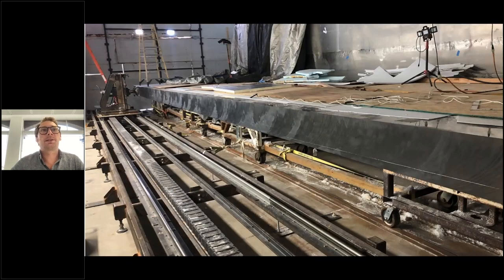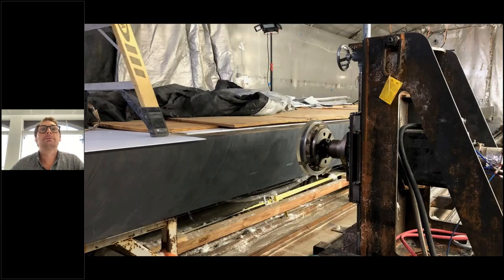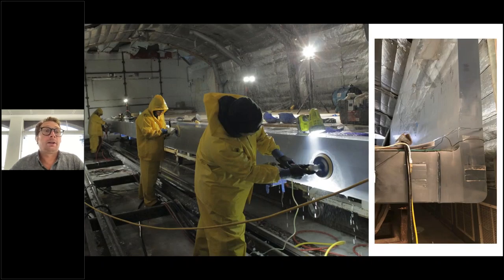And you can see here that the slab on the right-hand side is supported on tracks, so it could be wheeled out and turned around by a crane, so each side can be accessed. And you can see the milling machine, or another milling machine on the left-hand side, which is milling that vertical surface. Another close-up of that. After that, the guys get out the pneumatic polishers just to remove the residual scratches from the machine polishing.